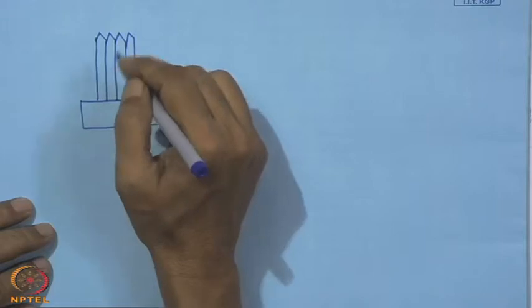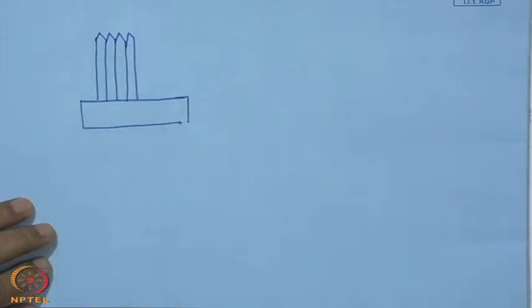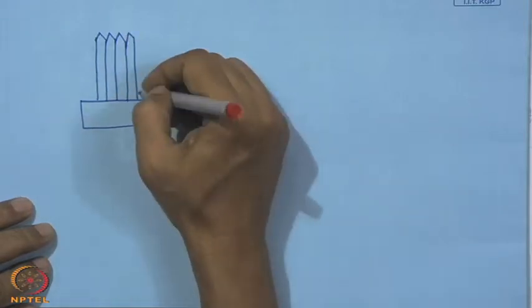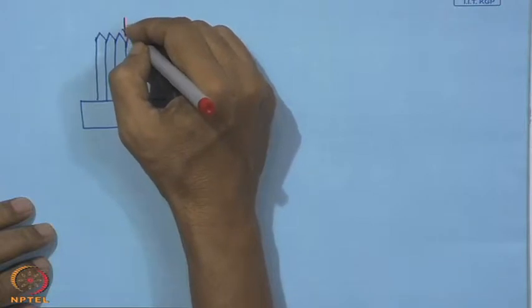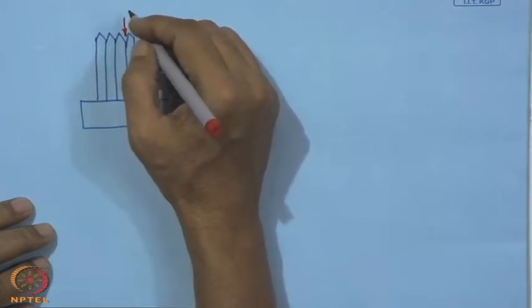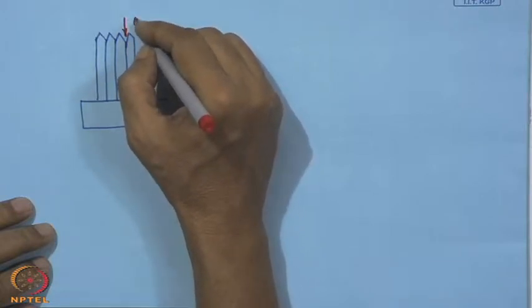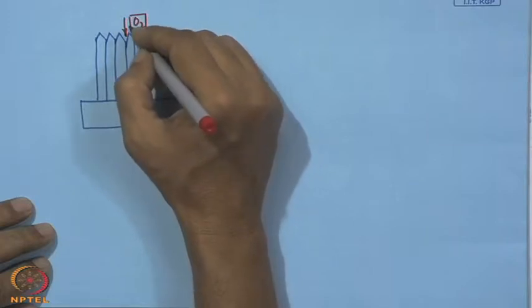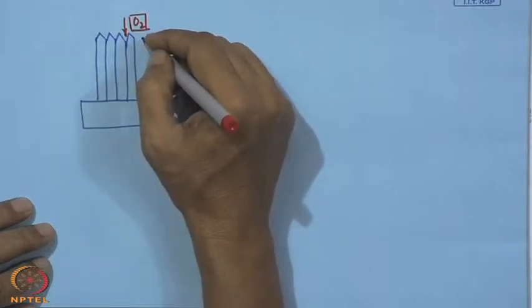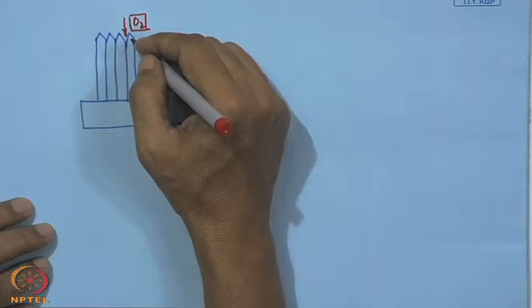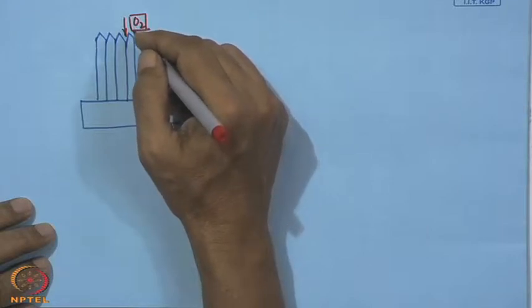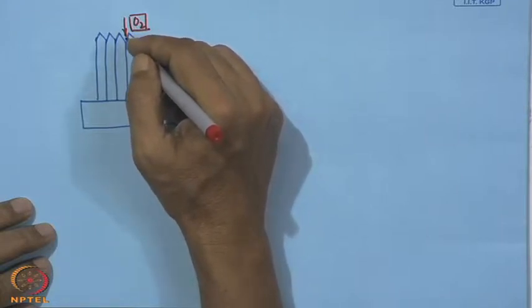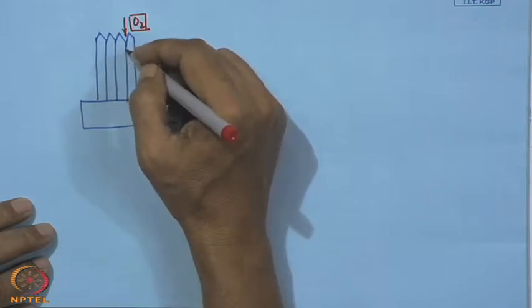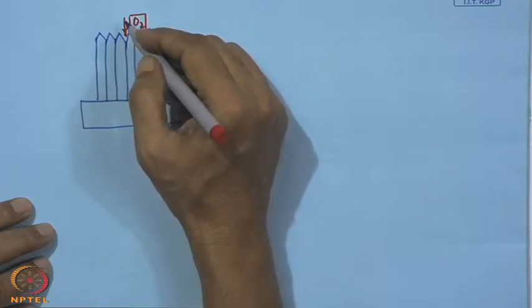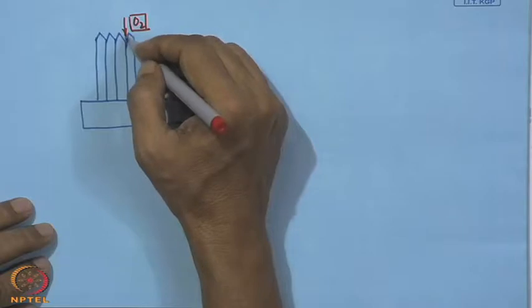So, if this is the orientation, and these are the basal planes like this, then there is also attack from the atmospheric oxygen, and that can also damage the coating. So, when this edge plane is parallel to the substrate surface, in that case also we can have oxygen attack in this way.